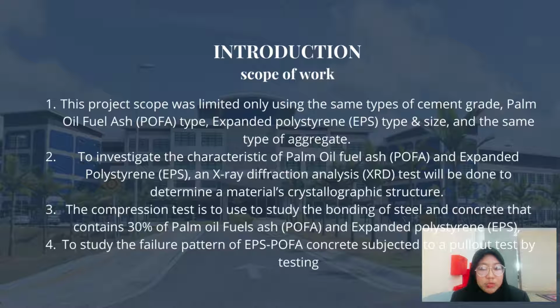Okay, for the scope of work, this project scope is limited to using the same type of cement grade, palm oil fuel ash POFA type, expanded polystyrene EPS type and size, and the same type of aggregate. It also investigates the characteristics of palm oil fuel ash POFA and expanded polystyrene EPS. The test done for this characteristic is X-ray diffraction analysis to determine the material crystallographic structure. And next, the compression test is used to study the bonding of steel and concrete that contain 30% of palm oil fuel ash POFA and expanded polystyrene EPS. And last is to study the failure pattern of EPS POFA concrete subjected to a pull-out test.